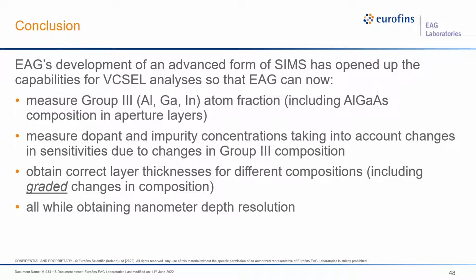So in conclusion, EAG's development of an advanced form of SIMS has opened up new capabilities for VCSEL analysis so that EAG can now measure group 3 atom fraction, including aluminum gallium arsenide composition and aperture layers, measure dopant and impurity concentrations, taking into account the changes in sensitivity due to group 3 composition, obtain correct layer thicknesses for different compositions, including graded changes in composition, all while maintaining nanometer depth resolution.